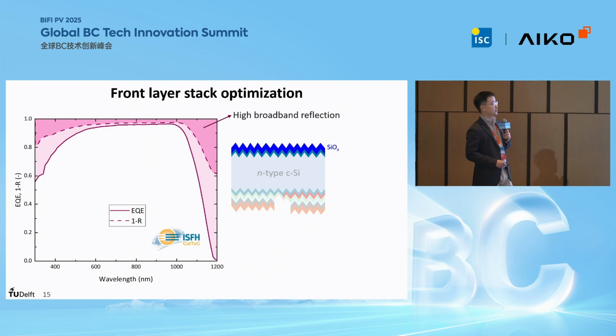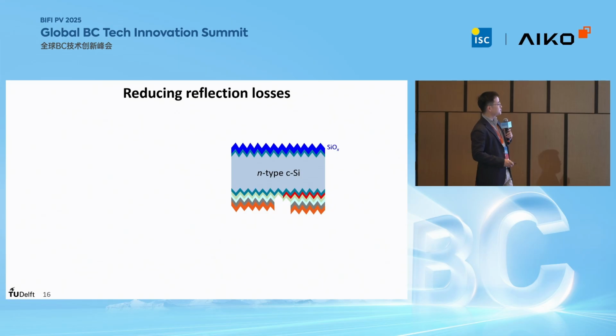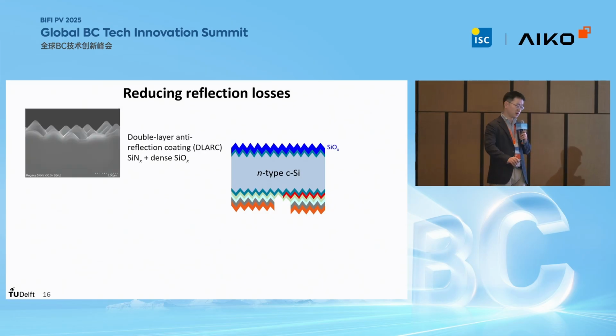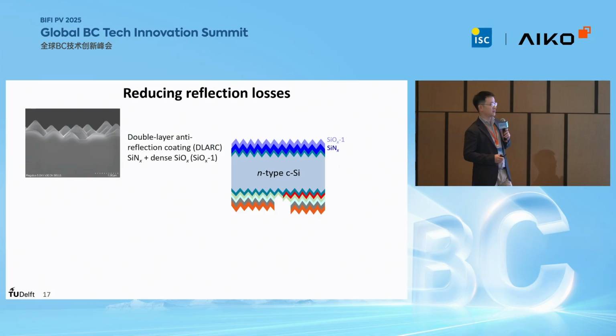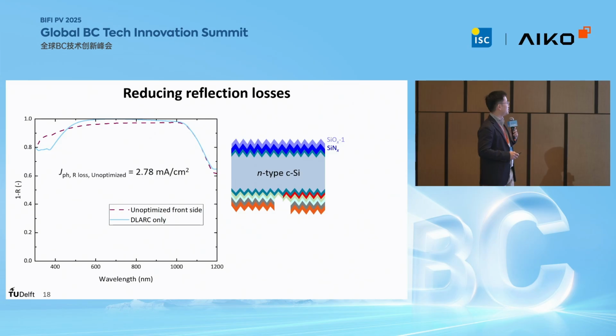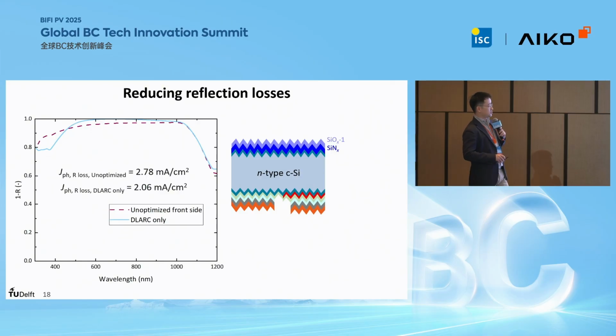And next, let's address the high broadband reflection. In this case, we have a reflection loss that is around 2.8. And then it's very natural that people think of optimizing refractive index grading. So instead of the simple silicon oxide layer as the anti-reflecting coating layer, we built a double-layer anti-reflecting coating combining silicon nitride and silicon oxide to form a better refractive index grading. In this case, this double-layer anti-reflecting coating can still exhibit the morphology of the standard textured silicon. And with this double-layer anti-reflecting coating, we can see from the 1 minus reflectance curve a much improved reflectance behavior of such device, especially in the middle wavelength range. And this leads to around 0.7 milliamp per square centimeter reduction of the reflectance loss.